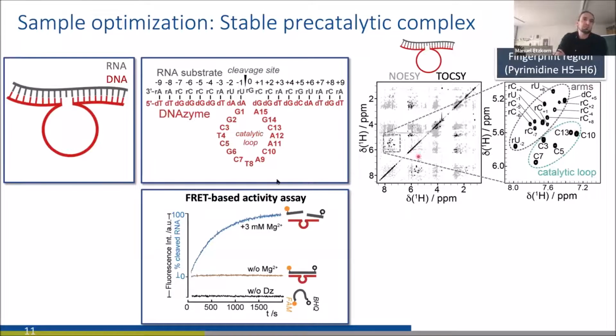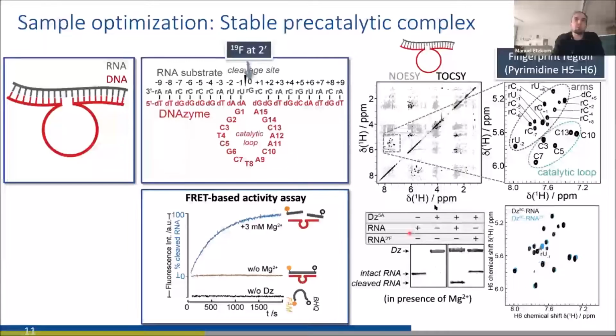Of course, since magnesium plays a critical role in activity, it would be nice to also investigate the complex in the presence of magnesium. To realize this, you can stabilize the complex by substituting the 2' position with fluorine, which makes the cleavage no longer achievable. You see in the NMR data that it only directly affects the surroundings of this substitution, and it does not affect the overall structure of the complex.